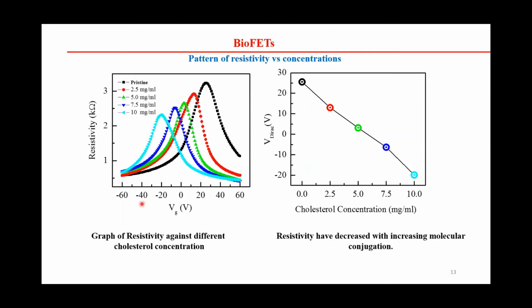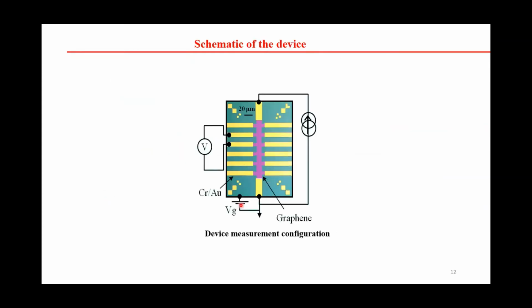In the case of a BioFET, if we have graphene, we can also use other 2D materials like MoS2, molybdenum disulfide, or tungsten disulfide, or you can make a combination like a heterostructure. We can choose this kind of thin layers as the channel material. What we will see is, on the bottom side we have the gate voltage, and on the left side we have the resistivity. In the pristine case, we apply the gate voltage on the bottom.